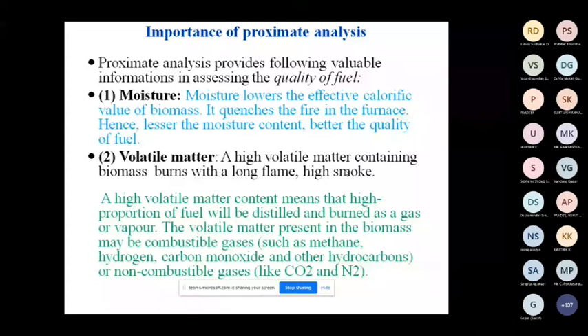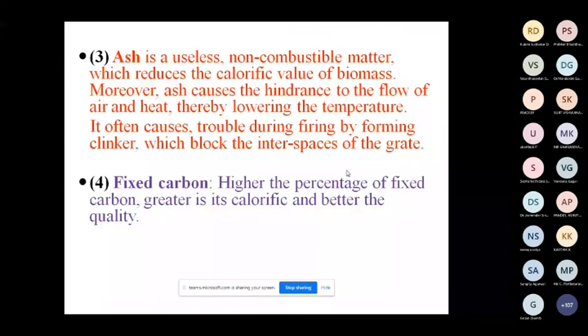Ash is a non-combustible matter which reduces the calorific value of the biomass. Moreover, ash hinders the flow of air and heat, thereby lowering the temperature. It often causes trouble during firing by forming clinker which blocks the interspaces of grate-fired boilers. Ash causes a lot of problems: slagging, fouling, deposition, corrosion. We'll be dealing with ash-related issues finally. Then fixed carbon: the higher the fixed carbon, the greater the calorific value and the better the fuel quality. So the primary basic input is your proximate analysis.